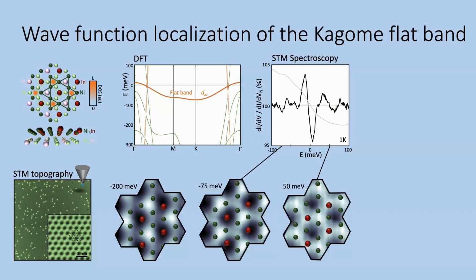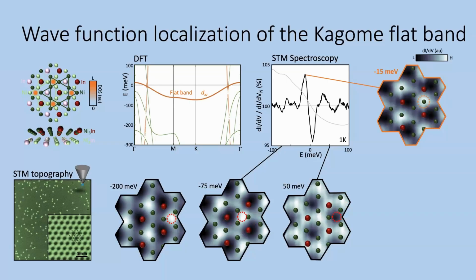But now we can examine where indeed it is localized. So this is super resolved density of states, taken at different energies of this lattice. And what you see is that far away from the Fermi energy, below and above the Fermi energy, the wave function localizes on or off the triangular corner triangles of the kagome lattice. So all these distributions respect the underlying symmetry of the kagome lattice. But then when we image the wave function at the peak, where we believe the peak is related to the kagome flat band, we find a distribution that does not agree with the prediction of the DFT. Basically, the wave function localizes on a nickel ion, which is not where it should be, according to a single particle calculation.